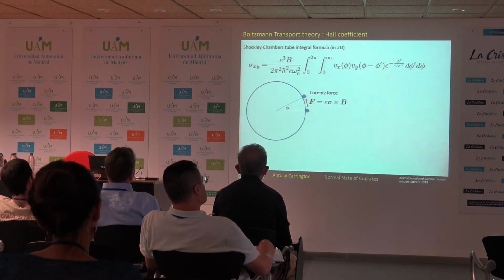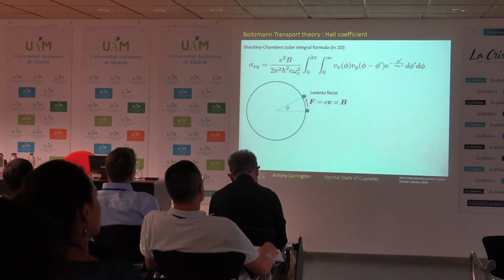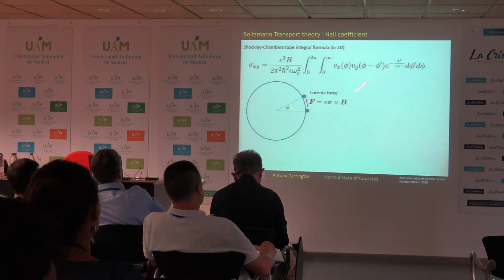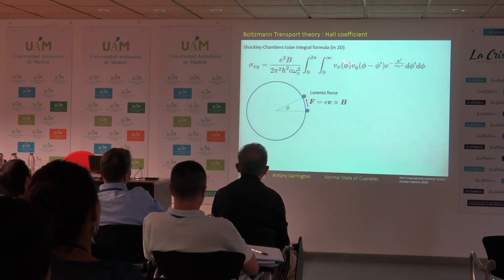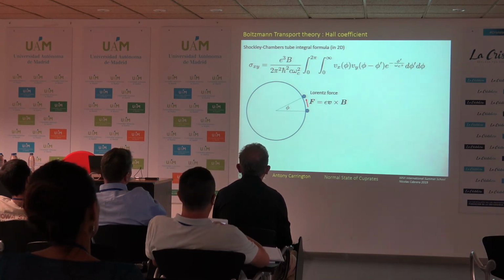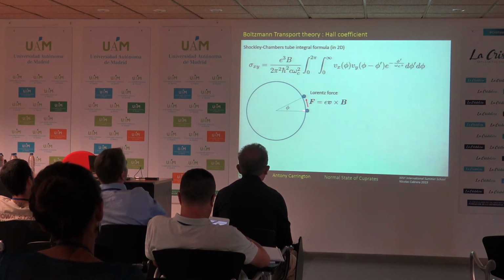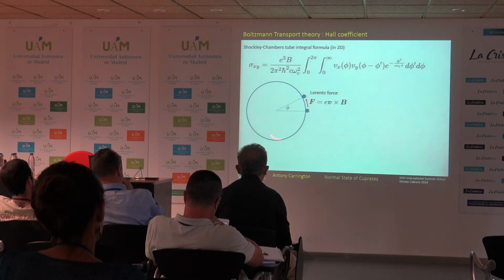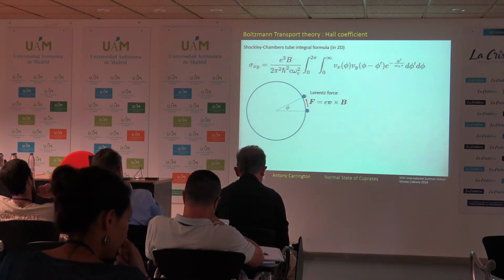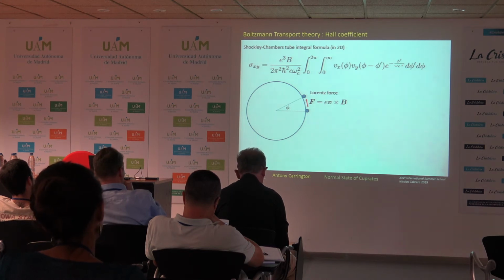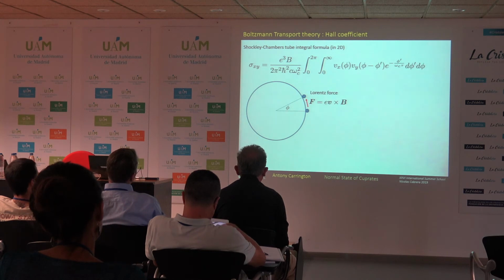Okay, so now we're going to move into a little bit of Boltzmann transport theory to try to see how we can understand what's going on here. So I started off by just writing down the Shockley-Chambers tube integral formula for the Hall conductivity. What happens when you apply a magnetic field is that you have a Lorentz force on the electron, and as v_F is always out this direction, the Lorentz force is always perpendicular to it, so it makes the electron go around the Fermi surface. Okay? So the Shockley formula is a very nice one because it's valid in low field, but also very high field. And you can understand exactly what's going on here.